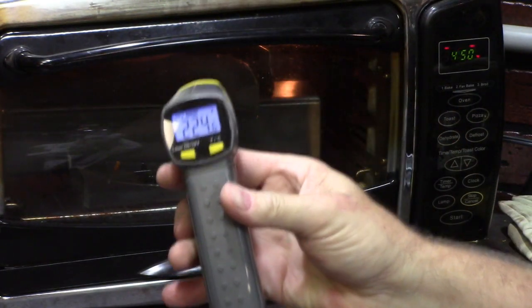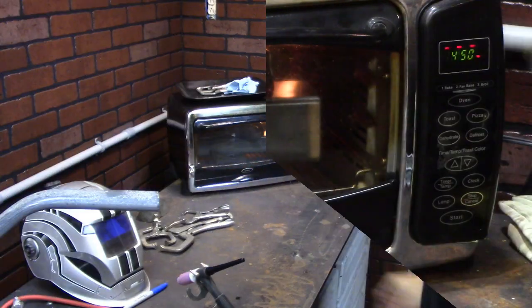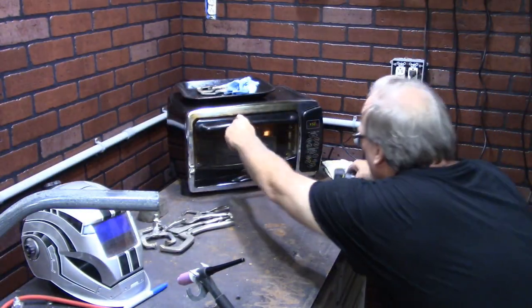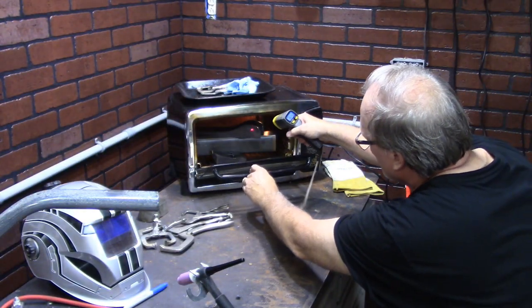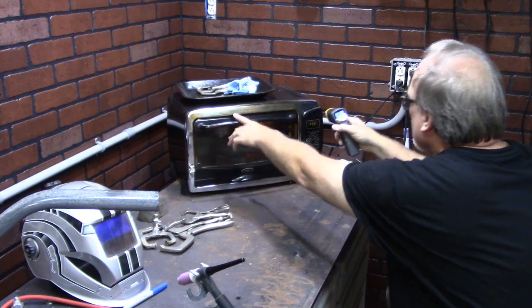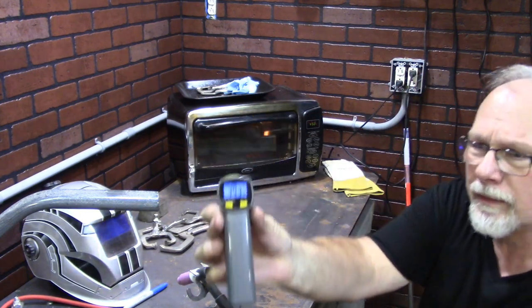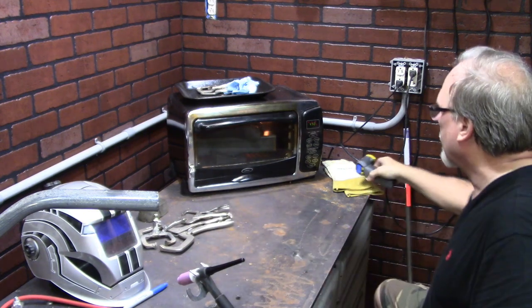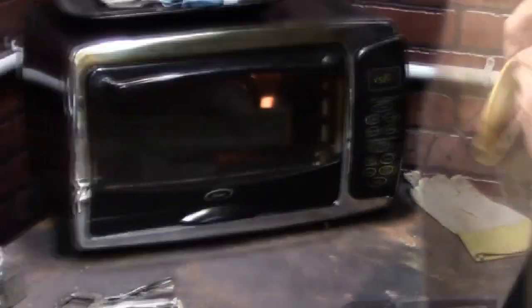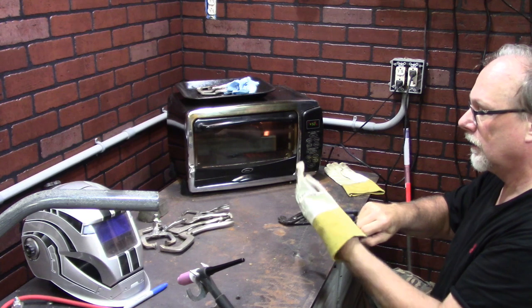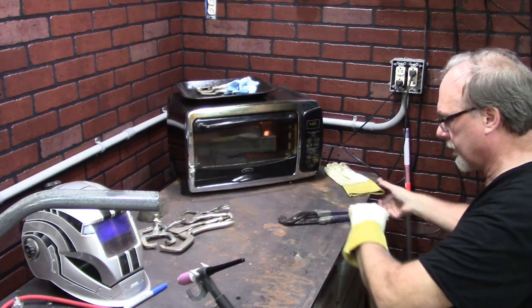Now I put this in there for over an hour to make sure I had good saturation. It took about 20 minutes to get it up to 200, and it took a little over an hour, I guess, hour and a half, to get it to just about 400 degrees, and that's the best it was going to go. So that's what we'll work with.